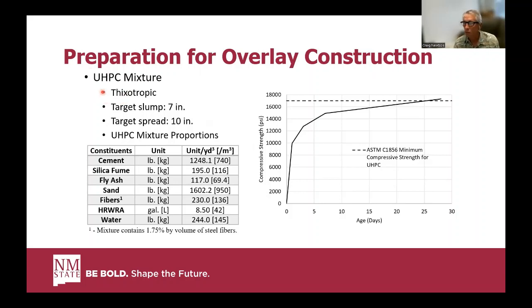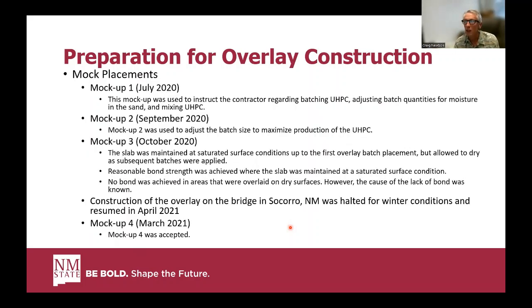So we got that. We got the properties that we wanted with the mix design there. Target slump was 7 inches. Target spread was 10 inches. We had the ingredients down here in the mix design, and basically what we were targeting was minimum strength for UHPC, 17,000 psi, and our mix was at like 17,320 psi. So we had a mix design that was functional for us.